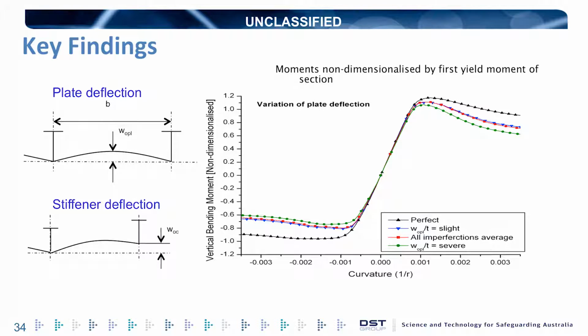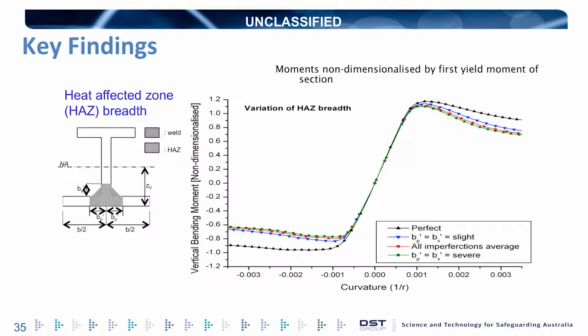And again here you can see for the plate deflection, the black line is the perfect ship structure. And again, Joe and Paik looked at slight imperfections, severe imperfections and an average imperfection, and he looked at all imperfections together. So you can see here for plate deflection of both the stiffener and the plate, there's a significant drop in the ultimate strength of the ship's structure by having those deflections. So if our welders give us lots of deflections, etc., it reduces the strength of our ship, which again impacts the ultimate strength, which impacts the distance that we can have for weapons effects, etc. Again here you can see the heat affected zone breadths.